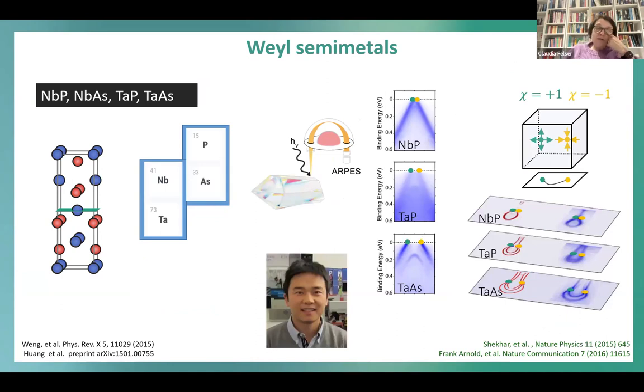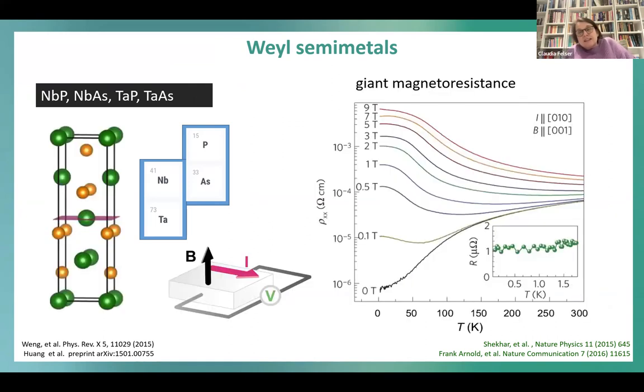So this was this Fermi arc I told you, and we simply focus now also on the right side. So you see the red lines, the red pictures are calculations which Binghai Yan did, and the yellow and the green dots are again the Weyl points, and the blue pictures are exactly the experimental results, and it shows very nicely the Fermi arc, this half moon kind of surface state. And in the middle, you see the nice linear dispersion. And you see, even if you go from niobium to tantalum arsenic, the spin orbit coupling, the relativistic effect, becomes larger, and therefore the splitting of spins. And also the distance between the Weyl points depends strongly on the spin orbit coupling. So, Christina, you should look for heavy Maxine phase. Okay. So, the next slide shows then what is also typical.